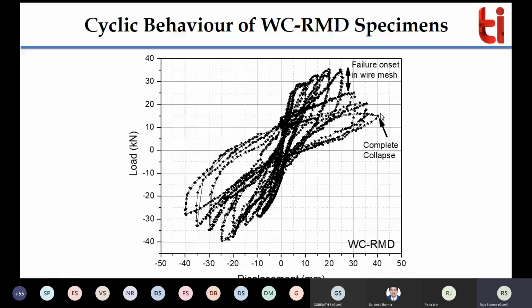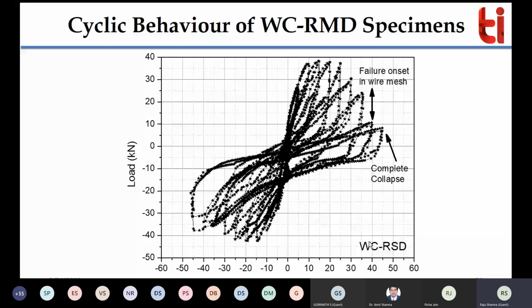And when you see this, it should be RSD, so the heading should be RSD, I apologize for that. So RSD shows the maximum load capacity nearby 40 kilonewton, and you have 45 displacement capacity, and you can see that the wire mesh failed somewhere over here, and then we got the complete failure nearby 45 displacement, and the residual strength in the specimen is approximately 9 kN, right? So this we got actually from the testing, and this is the failure pattern which you observed.